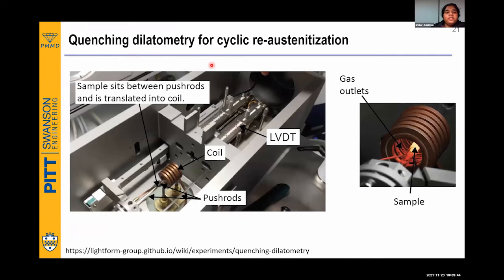The quenching dilatometer is a very interesting instrument where you have these 2 push rods, where you place your sample. The sample is going to be sitting between these 2 push rods, and you will have a copper coil which is slid over it. In the middle of the sample, you will have a thermocouple that is welded on to take care of the temperature. And this LVDT is going to record the length changes. LVDT is known for measuring very sensitive length changes.